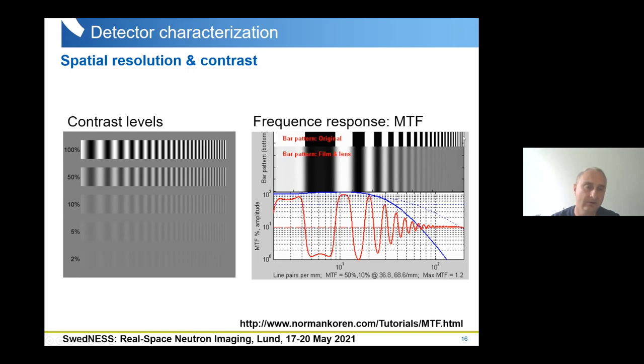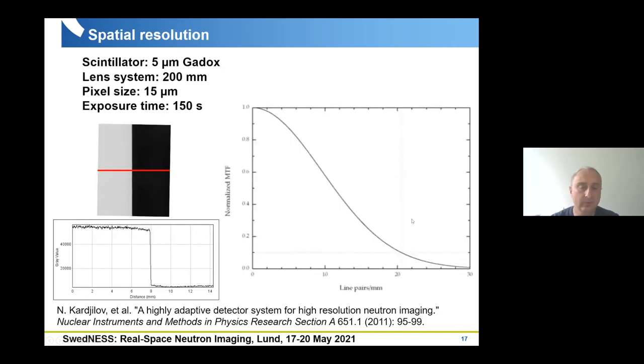And this can be seen here. This is the original pattern. And after the contribution from the detector, or let's say the response function from the detector, is leading to a smearing of this pattern. And with the increase of the line pairs, we see that we lose contrast, or the difference between the maximum and minimum intensity is reduced. And this is the definition of the modulation transfer function, where the reduced contrast with the increased frequency comes down to 10%. So how does this work in reality?